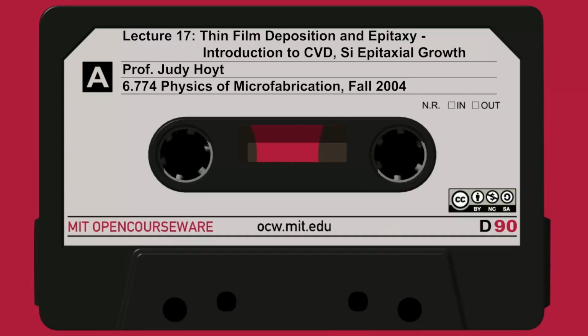Just taking a little more zoomed in look at this more modern reactor on slide 23. This is that same picture. The only difference is here we're showing a single chamber right here, one of the chambers. And this green object is meant to be a wafer that is sitting on a susceptor that's spinning. So the wafer is spun at high velocity, say 30 revolutions per minute, to try to get good uniformity across the wafer. And the gas comes in here through a series of injectors as a plane, flows across the entire wafer. So the inject is over here, and it flows laterally across, and the exit or the exhaust would be over here. And the wafer spinning.